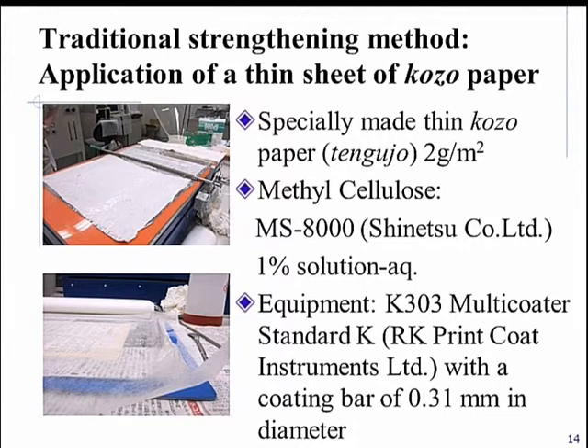The adhesive used was an aqueous solution of 1% methyl cellulose. A multi coater with a coating bar of 0.31 millimeters in diameter is used to apply the adhesive.